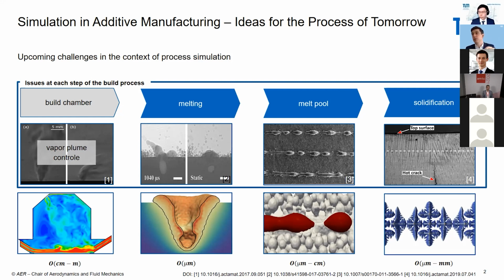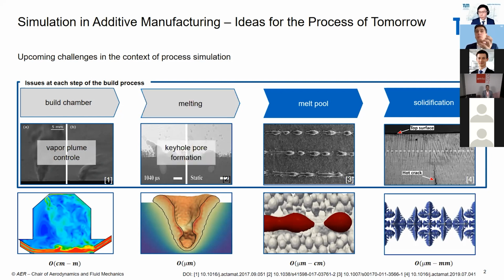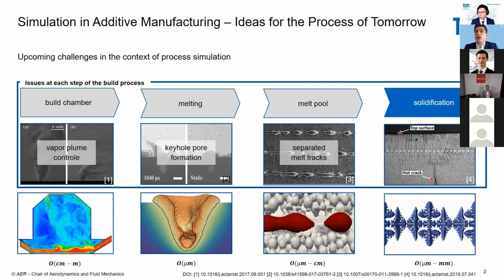We want to resolve the keyhole or the melt pool where the laser interacts with the melt. And there we want to, for example, investigate, understand, or make sure that the keyhole pore formation can be suppressed. Then a little bit bigger is looking at an entire melt pool. We can simulate the tracks where we have, for example, balling. We want to study the stability of these films, of these tracks, and that's what you can simulate.